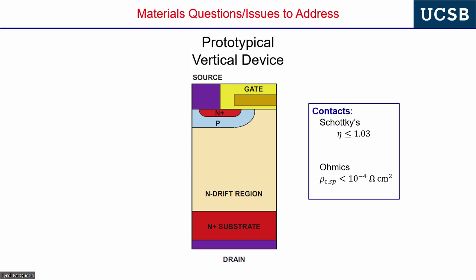In semiconductors, if we have diodes, we like to have Schottky diodes, very simple 2-terminal device where we have a heavily doped base region for high conductivity. We want to make a good ohmic contact to this, and we have a very lightly doped region. If it's a Schottky diode, we would not have this structure here. This is just a prototypical vertical 3-terminal device. We would just have a Schottky contact, okay? And usually the Schottky quality is determined by what we call the ideality factor, okay, and how close we also come to the predicted reverse saturation current, J0.